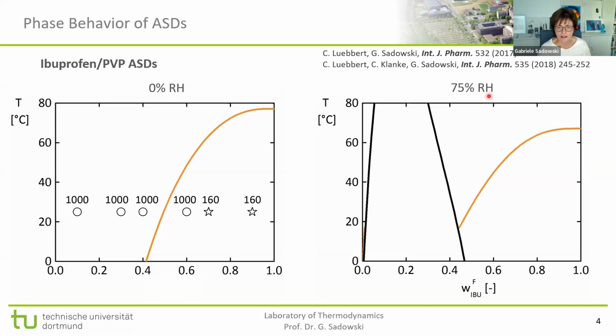If we go to 75% RH, then our prediction says that we have a solubility line, but now we also have a liquid-liquid demixing. And the liquid-liquid demixing again happens on the left-hand side, and this is because this is where the polymer is. And the polymer is the one that absorbs a lot of water at high RH values, and that means here in samples on the left-hand side, we have much more water than in the hydrophobic ones on the right-hand side. And so the calculation says this system will demix at the more hydrophilic samples, and these are the ones to the left in this diagram.